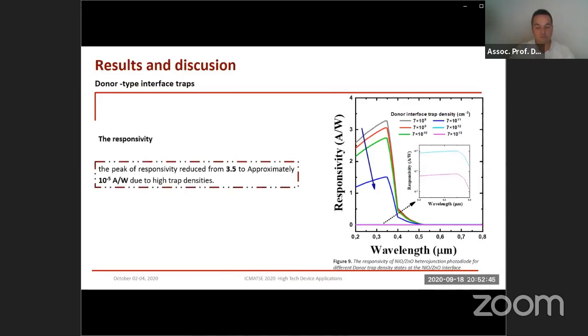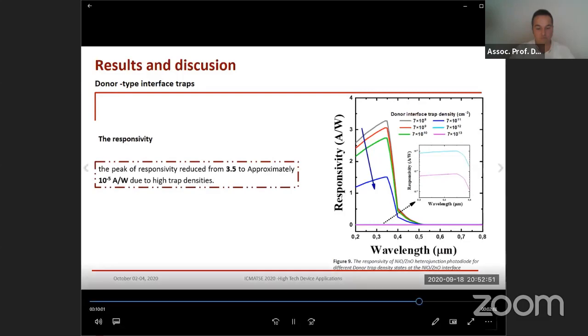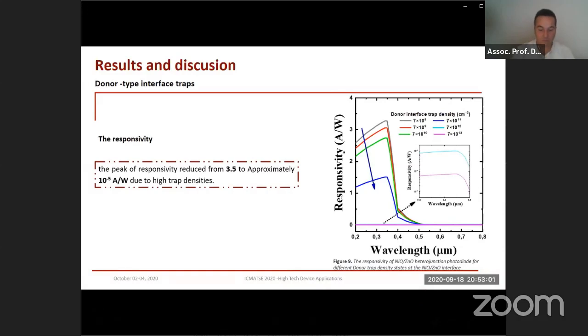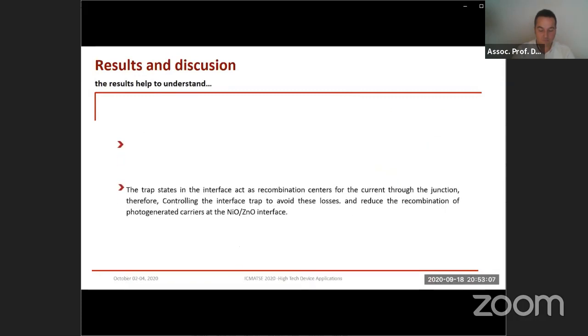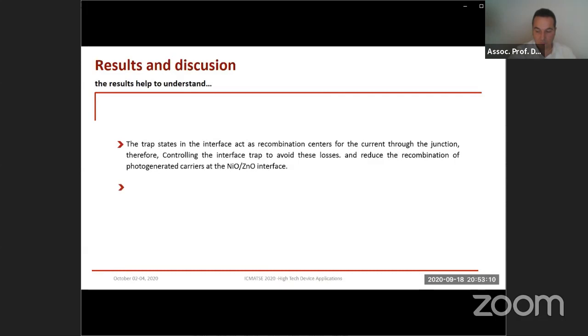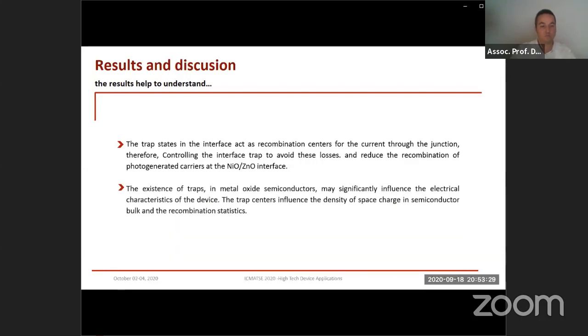The peak of responsivity reduced from 3.5 to approximately 10^-5 A/W due to the high trap densities. These results mirror the behavior of a nickel oxide-zinc oxide heterojunction with the presence of acceptor or donor traps. The results help us understand that the trap states in the interface act as recombination centers for the current through the junction. Therefore, we must control the interface traps to avoid these losses and reduce the recombination of photogenerated carriers at the nickel oxide-zinc oxide interface.